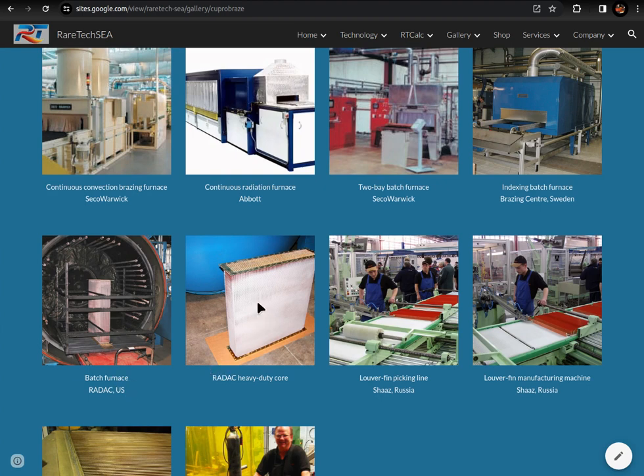They had very, very heavy cores. And it's very difficult, also with these kind of side rails, to support it and everything else. To get better tube to header joint integrity, they would prefer to stand it this way. So you actually get your braze alloy in here and braze alloy in there nicely. And this is the kind of furnace that he put together. And then you would close it in.